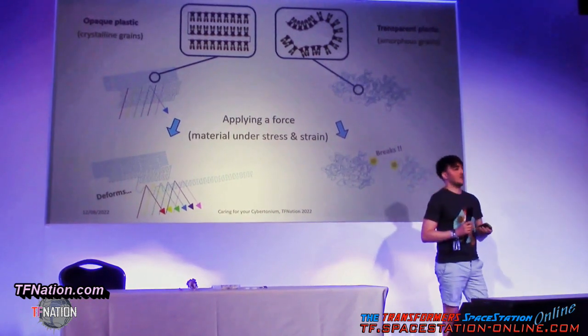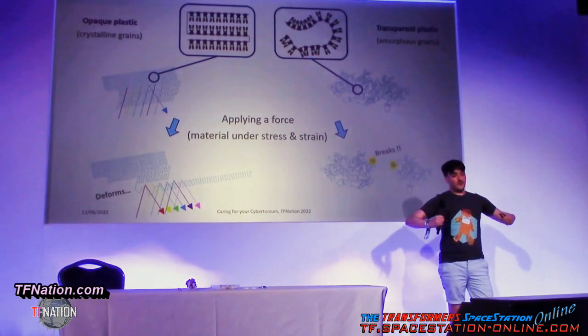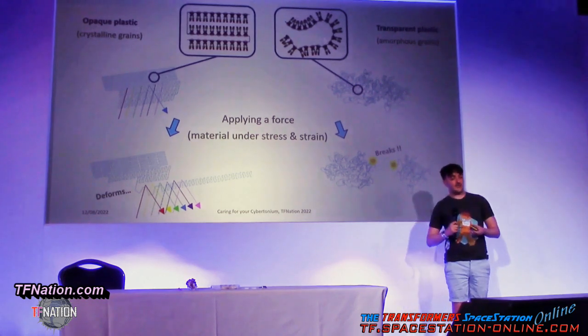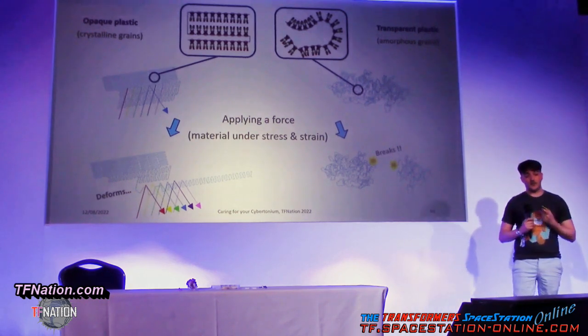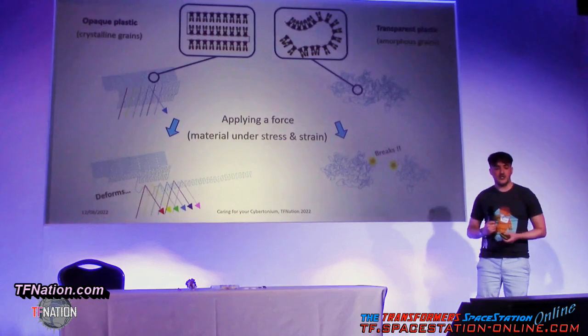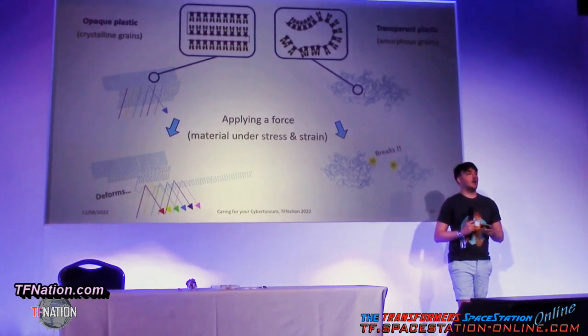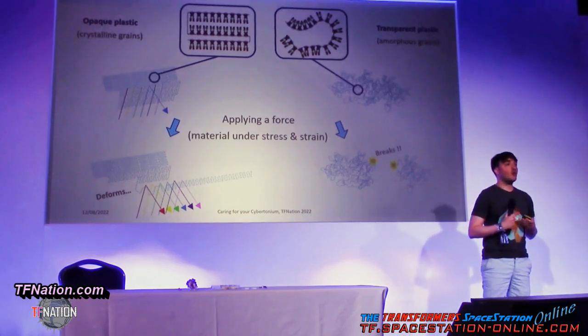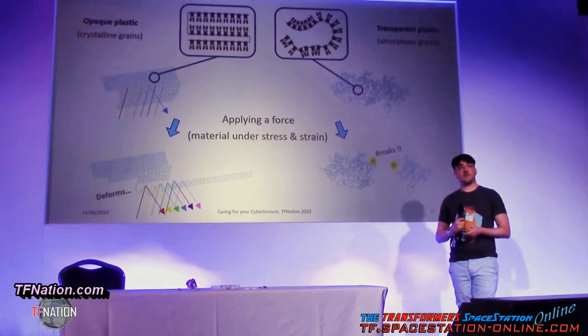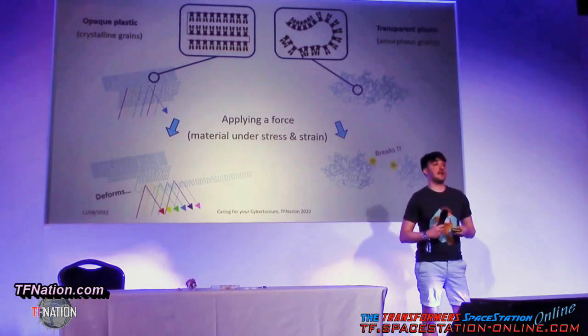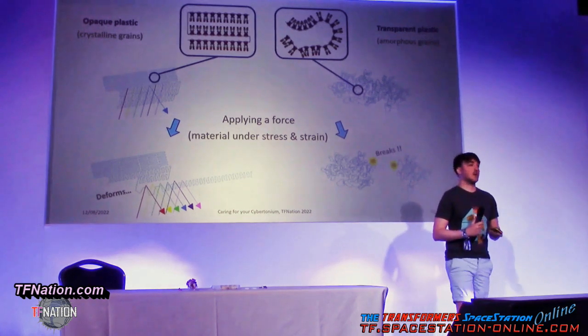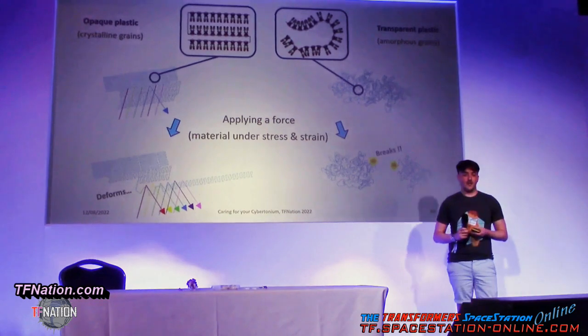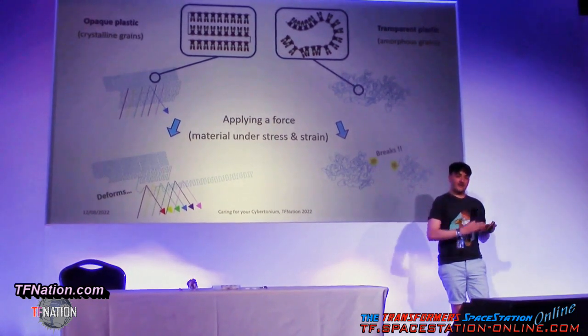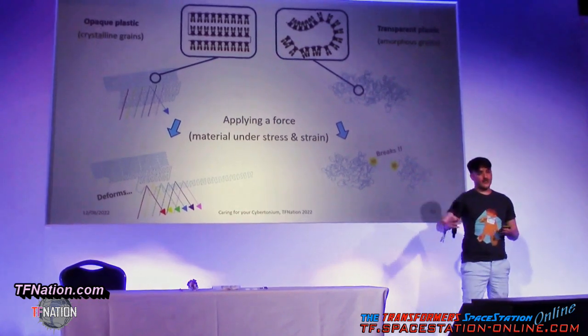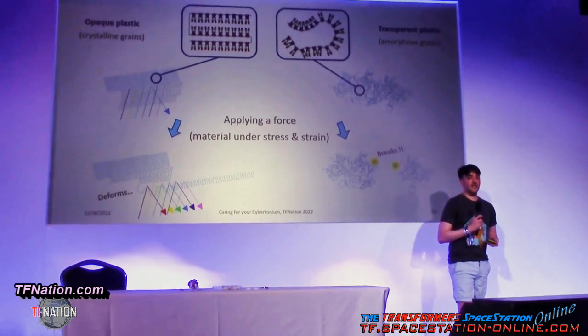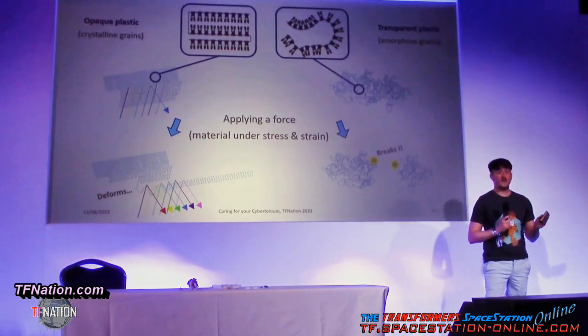When you deform it, what happens with the crystalline types of plastic is you pull them and the chains start to unravel. So they slide against each other, but still try and maintain as much as they can the structure. And by changing that structure, it changes the refractive properties. And suddenly, all of the colours in the spectrum are not being absorbed, all of them are being reflected. And if all of the colours along the visible spectrum are being reflected and meet your eye, that is white light. And that's why stress marks look white. We probably have examples of different plastics across this range, but generally for amorphous types, it prefers to break, like you can see there as we discussed just before.